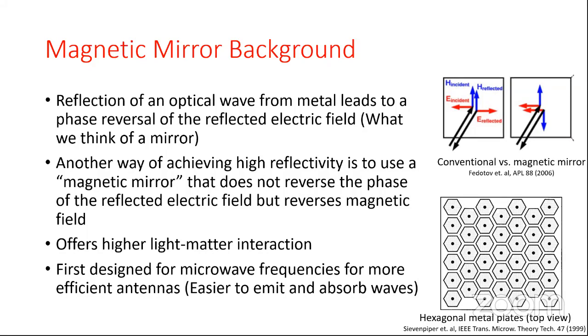However, there's another way of achieving high reflectivity, and it's to use a so-called magnetic mirror. It's similar, but works in a reverse way. So it doesn't change the phase of the electric field, however, it reverses, and for a perfect magnetic mirror, it changes the magnetic field portion by 180 degrees. And why it's important is it offers higher light matter interaction.